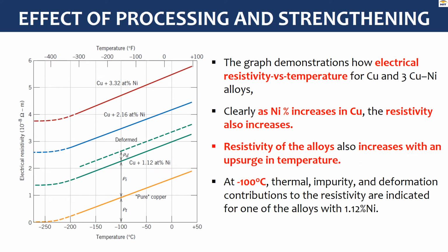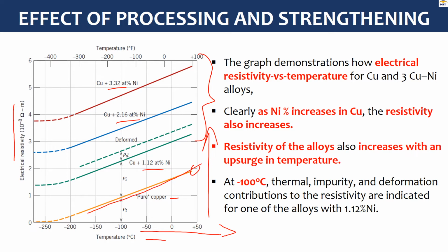now you can look at this graph, which shows again the relationship of electrical resistivity here on your y-axis, as well as the temperature on your x-axis. This is for copper and some copper-nickel alloys. We can clearly see here that as the nickel increases, here there is this one 0 nickel, 1.12 nickel, 2.16 nickel, 3.32 nickel. So we can clearly see that as the nickel increases, resistivity is also increasing. Then we can also tell from the x-axis, this is increase in temperature. As the temperature also increases, then there is also an increase in resistivity, hence the positive gradient of